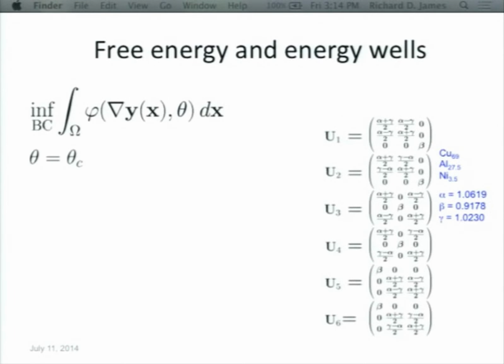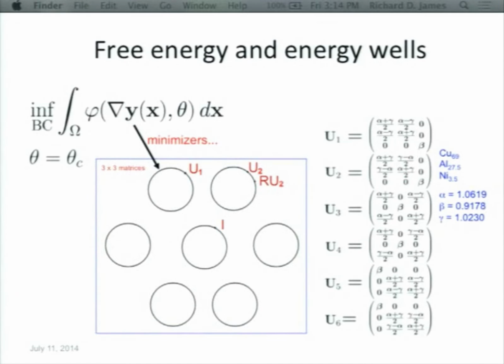Okay, so most of the things I'm going to tell you come from a description of the free energy of the material, which is a function of the deformation gradient, a 3x3 matrix, and temperature. The key point is it has energy wells. At the transformation temperature, phi is minimized by U1, and it's also minimized by any rotation matrix times U1 by the condition of frame indifference, and that's represented by this circle. Same for U2 and R U2, a rotation matrix times U2.